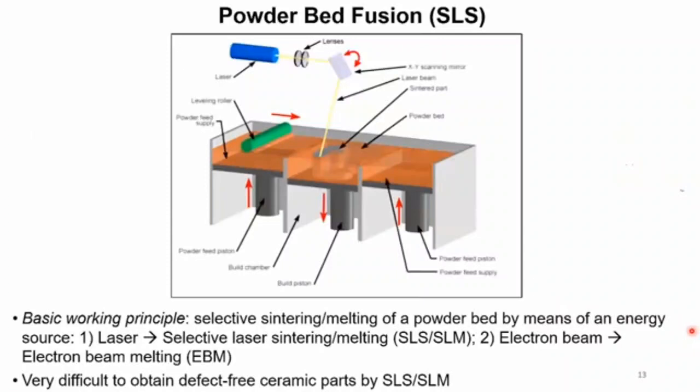Powder bed fusion is of course very famous for metal particles because you can either melt or you can sinter the metal particles very conveniently. There is good absorption of the laser radiation, and also high thermal conductivity, so there's no thermal shock.